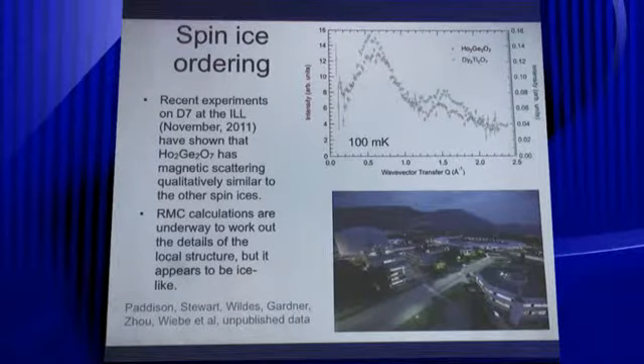And because holmium has this nice isotope compared to dysprosium, we actually made around 0.3 grams of this. It took Haidon about 6 months to make this sample, but we got enough to do a D7 experiment to see if it really is a spin ice or not. This is looking at the magnetic scattering that hasn't been scaled properly, but I'm showing you dysprosium germanate, holmium germanate compared to dysprosium titanate. And you can see that it has a characteristic spin ice-like neutron scattering profile. We're doing these reverse Monte Carlo calculations right now to work out the details of that structure, but naively it looks like that's a new spin ice.